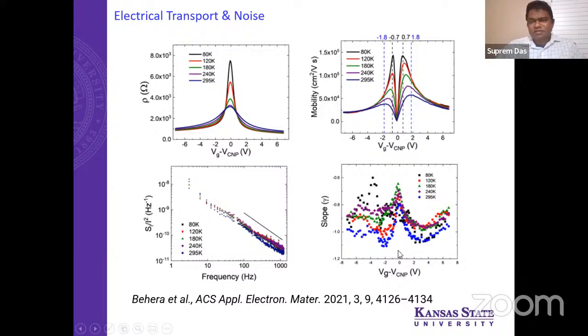But it's very interesting, if you look at this Dirac point and the slope of this, as I was saying, if it is 1, then it is 1/f. You can see the slope is not always 1. Actually, it can vary from -1, basically because it's decreasing, right? So if it is just 1/f, it will be a flat straight line. But look at this, at a Dirac point, you have a lot of variation. And that's why, in the beginning, I told you that graphene is very, very interesting, very, very different, because you see a lot of interesting things around the Dirac point. And this is really interesting.